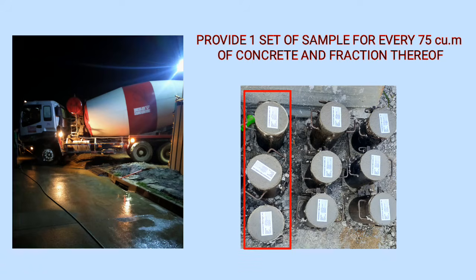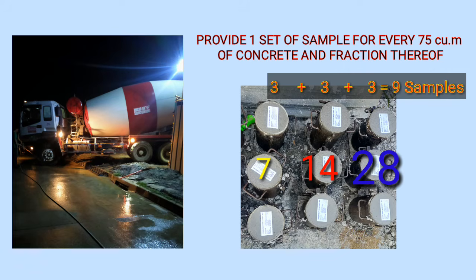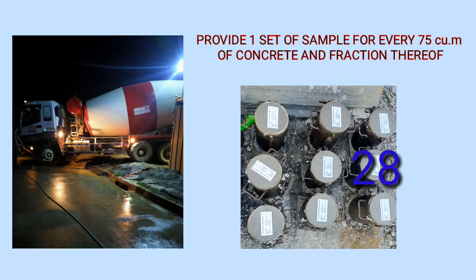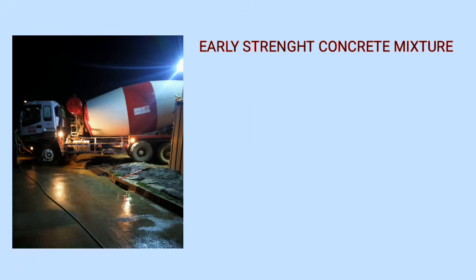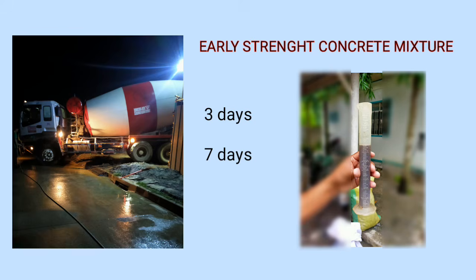Kaya kung magbabalak kayo magpa-test for 7 days, 14 days, and 28 days, kakailanganin mong kumuha ng 9 cylinders of sample for every 75 cubic meter of concrete mixture, or not more than 75 cubic meter at random for every transit mixer. Alam nyo ba na ayon sa pag-aaral, ang ordinary mix of concrete ay tumatagal hanggang 28 days bago ito umabot sa maximum na strength nito. Kaya lang tayo nagkakaroon ng early strength na 3 days or 7 days because of admixtures.